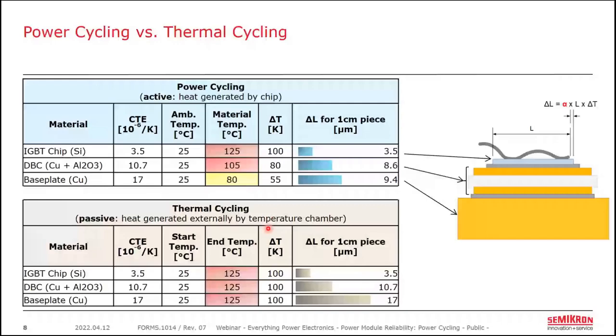But the copper base plate, which only had a delta T of 55 Kelvin before, now has a 100 Kelvin delta T and a much larger change in length, here 17 microns versus that 9.4 microns before. So that base plate to DBC solder joint is potentially seeing a lot more stress than in the power cycling test. The thermal cycling test has value in evaluating construction techniques and is done as part of the qualification test the module manufacturer performs on a new module.